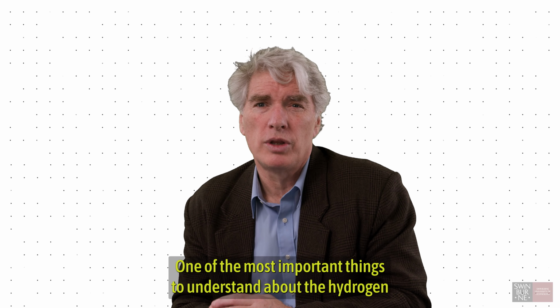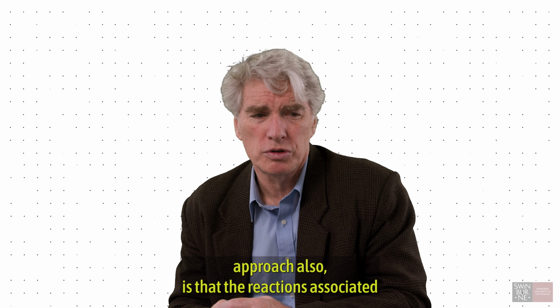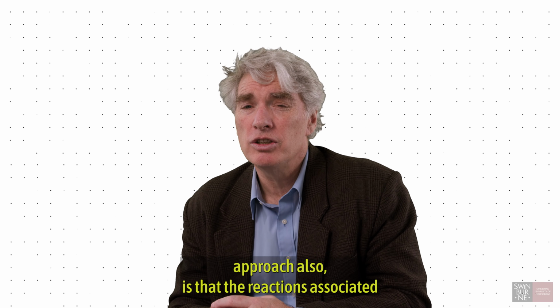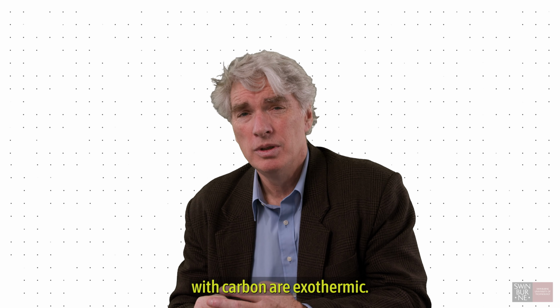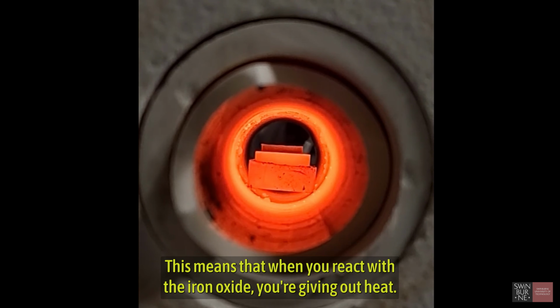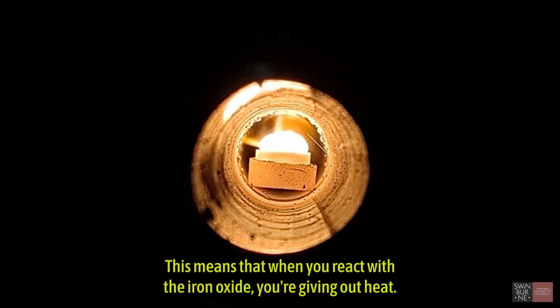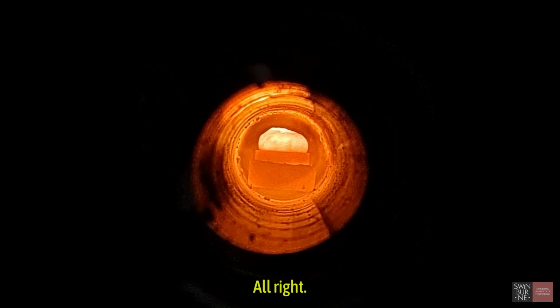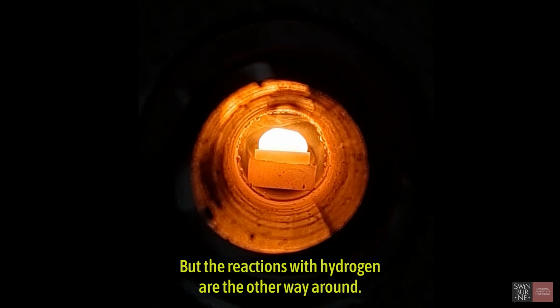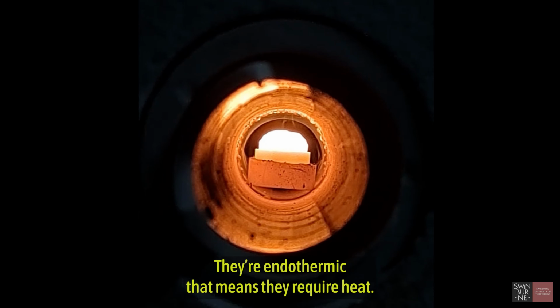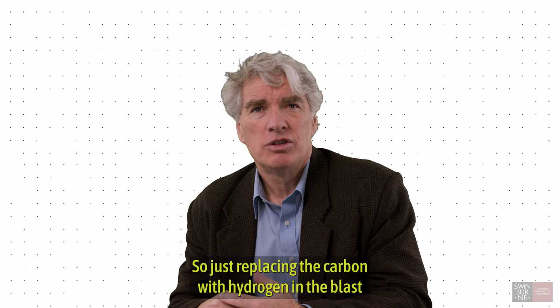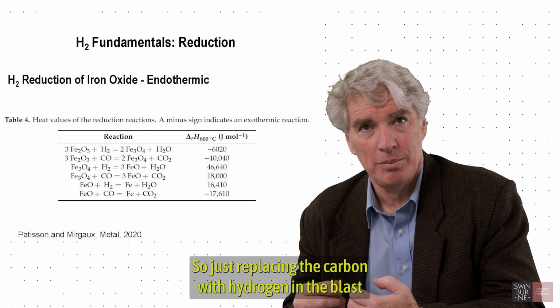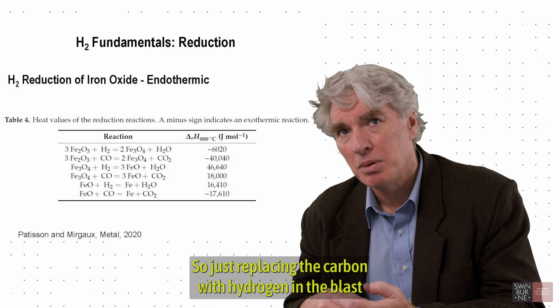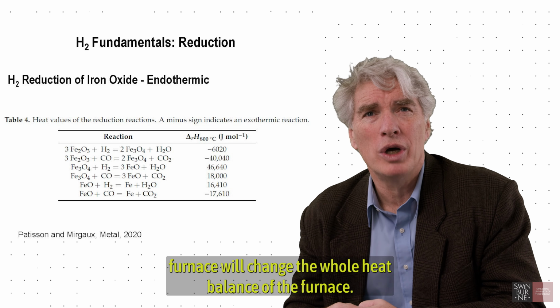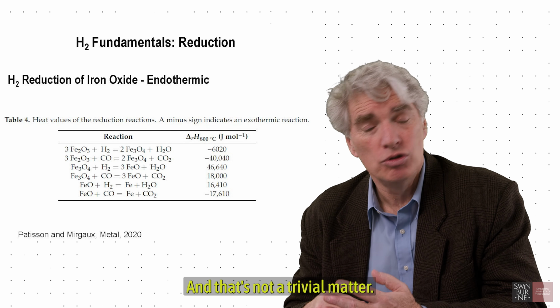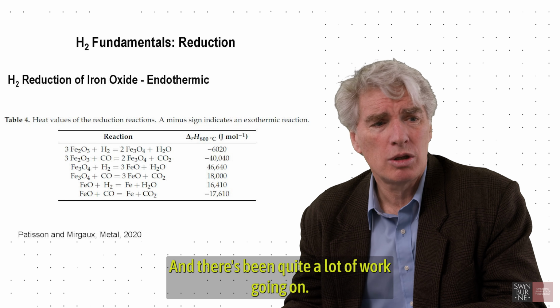One of the most important things to understand about the hydrogen approach also is that the reactions associated with carbon are exothermic. This means that when you react them with the iron oxide, you're giving out heat. All right? But the reactions with hydrogen are the other way around. They're endothermic. That means they require heat. So just replacing the carbon with hydrogen in the blast furnace will change the whole heat balance of the furnace. And that's not a trivial matter. And there's been quite a lot of work going on.